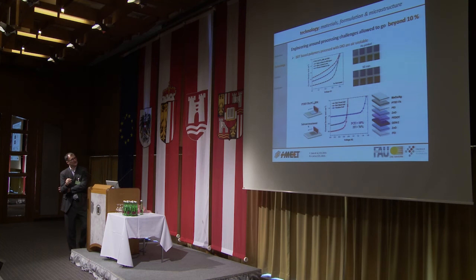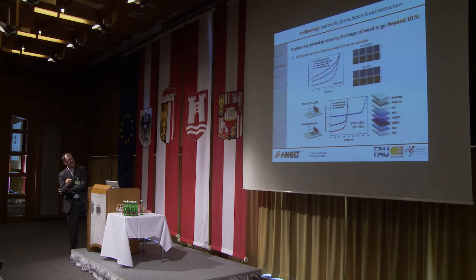And you can see here the pristine polymer, and you see it here in the blend with PCBM, directly after printing. And then even in a clean room at yellow light, we had it 15 and 30 minutes outside. And you can see here, no DIO additive, more DIO. And with the DIO, within minutes, it's gone and bleached.